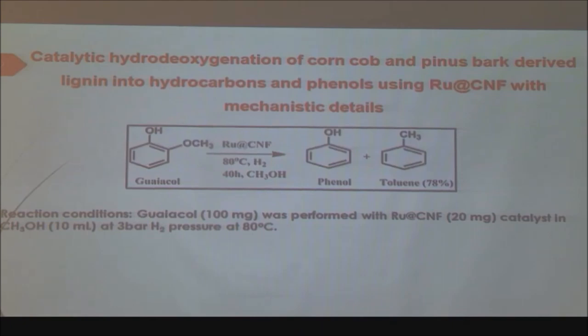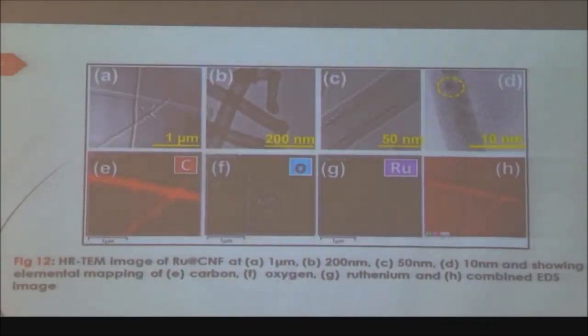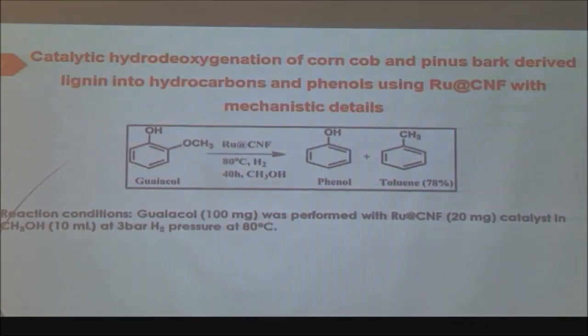Because we really want to be sure that there is no error in isolating the lignin from these two plant sources as well as the one that is available in the market. So we take three lignins and again started with the model molecule. One more after vanillin, we also try guaiacol, and this time we replace palladium with ruthenium, and of the carbon nanotube we just focus on one, carbon nanofiber.